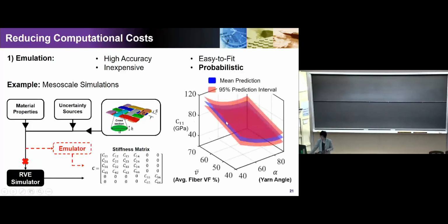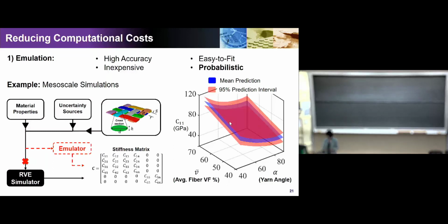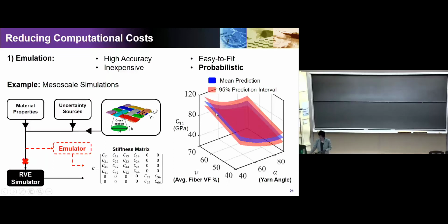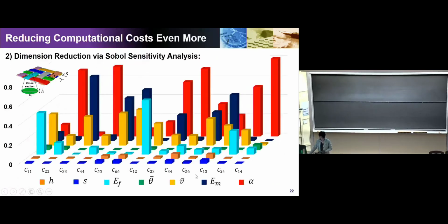One nice thing about the GP model is that it can quantify the uncertainty. It could also allow you to determine where you should pick more samples, because we always have a case where we do not have enough samples, so we have to decide how to do this sequentially. Based on a certain amount of samples, we could show the 95% confidence interval for C11 as a function of the average fiber volume fraction as well as the Yarn Angle. Here is one example of a statistical quantity. We could also use the variance of the volume fraction as an input to take care of the statistical quantity.